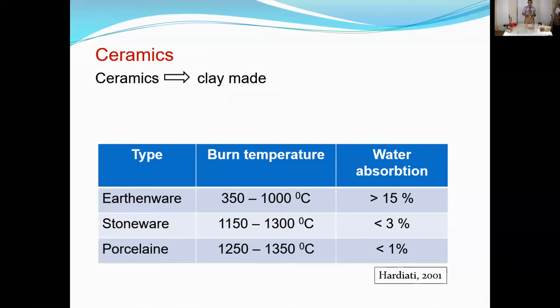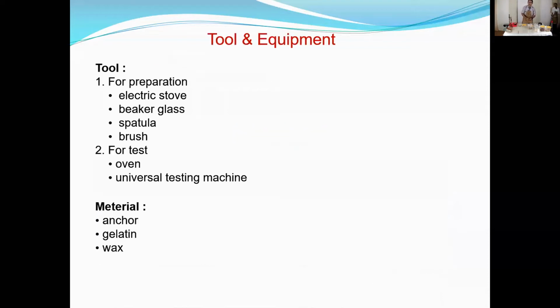What we did in our research, there are two types of ceramic: porcelain and terracotta. If it's from terracotta, the material has bigger pores. Therefore, you could accept more water. Well, porcelain is fired at a higher temperature. Therefore, with smaller pores, it absorbs less water.